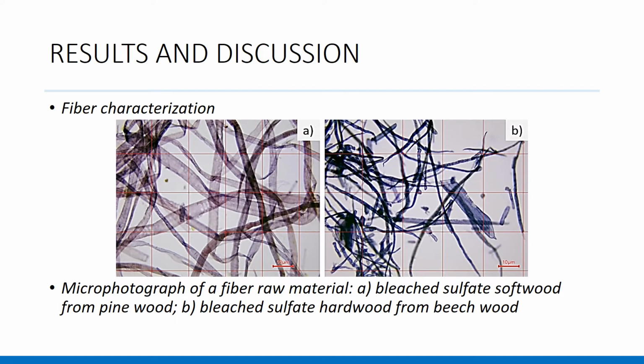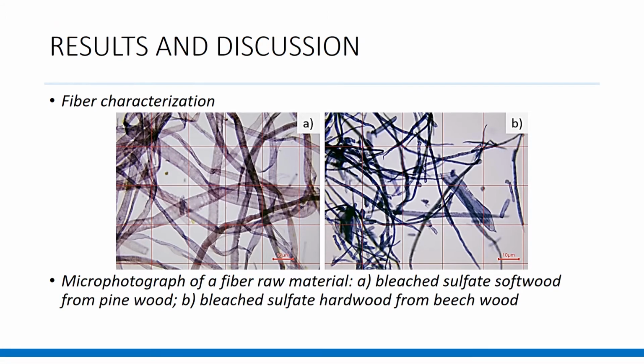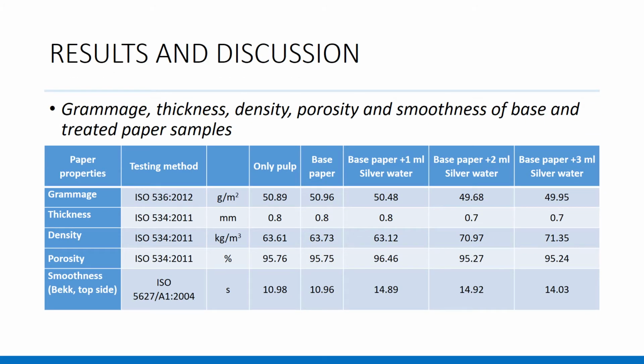As a result, from the fiber characterization with a microscopic analysis, it was observed that the bleached sulfate softwood pulp is from pine wood and the bleached sulfate hardwood pulp is from beech wood. From the data on the structure and dimensional properties of the base paper and the silver water treated papers, it is found that the addition of sizing agent and retention additive does not affect the smoothness of the paper.